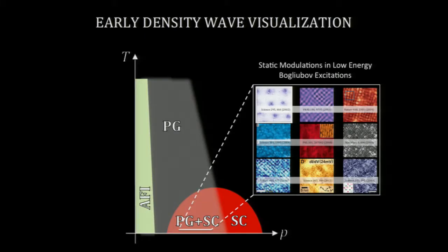A little bit later, STM showed in its measurements that the system really does have a modulated electronic structure. One of the earliest experiments was done by Jennifer Hoffman back at Berkeley, where they looked at superconducting vortices, and inside those vortices they see this modulated electronic structure. And then this was confirmed in the normal state and also in the oxychloride family of the cuprates.